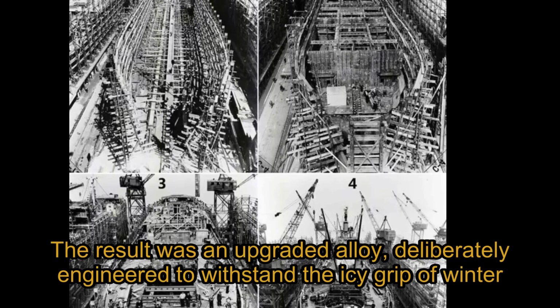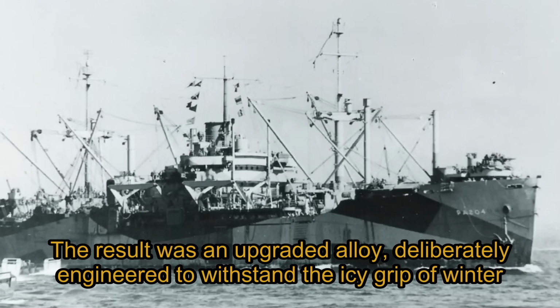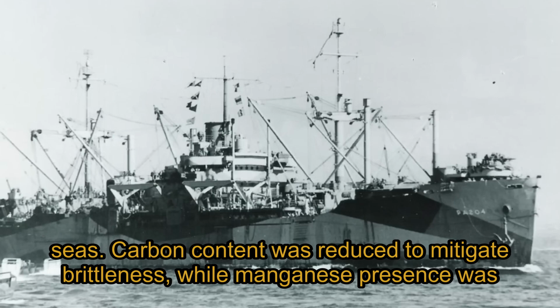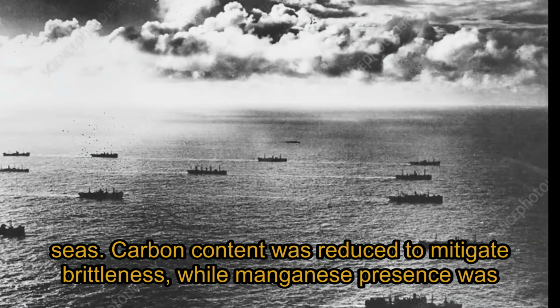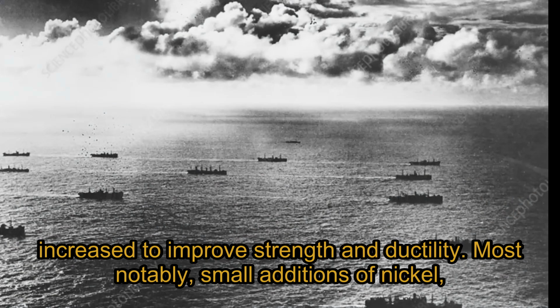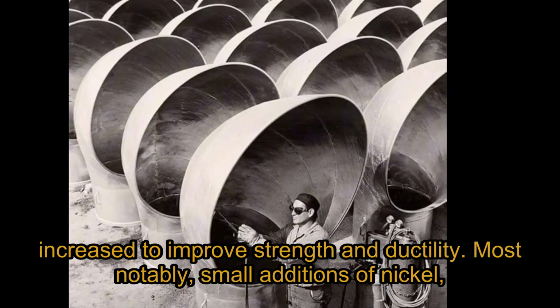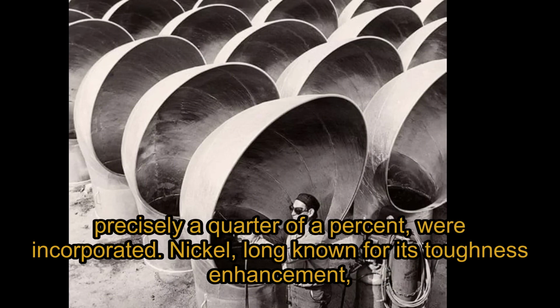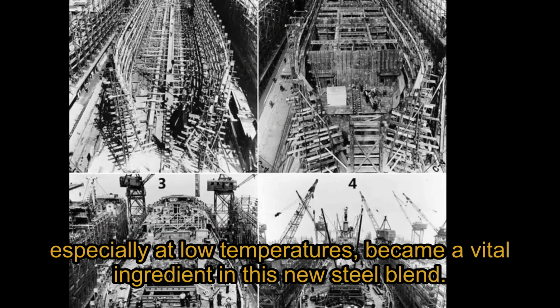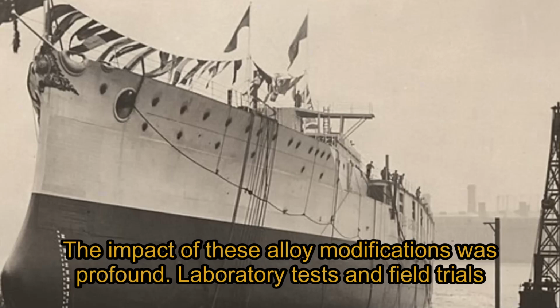The result was an upgraded alloy, deliberately engineered to withstand the icy grip of winter seas. Carbon content was reduced to mitigate brittleness, while manganese presence was increased to improve strength and ductility. Most notably, small additions of nickel, precisely 0.25%, were incorporated. Nickel, long known for its toughness enhancement, especially at low temperatures, became a vital ingredient in this new steel blend. The impact of these alloy modifications was profound.